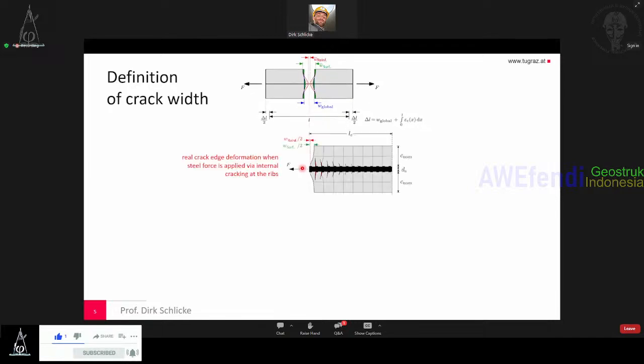If we look closer, we can see, well, this real crack edge deformation is subject to what we call internal cracking at the ribs. We have a load transfer from the rib to the concrete. The concrete is a porous and very fragile material, which gets internal cracks due to the contact with the ribs. If you pull out the bar, the rib gets into the concrete, makes internal cracking, as the deformation of the concrete is not possible without cracking in this size.